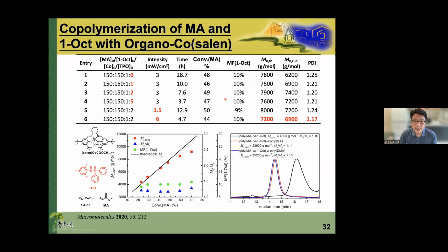And we found we can optimize the condition to get the mole ratio of 1-octene as 10%, and we got linear increased molecular weight, low polydispersity, so we can synthesize the copolymer of 1-octene with acrylate by cobalt mediated radical polymerization.